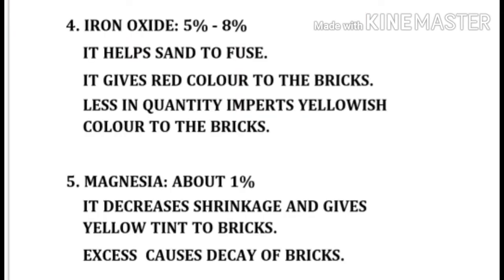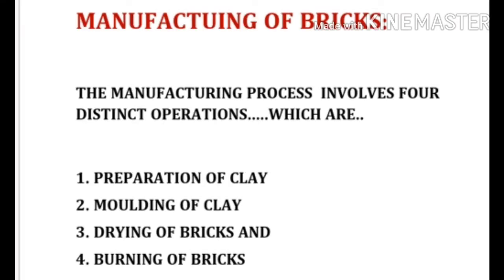Number three, lime — 4 to 5 percent. It resists shrinkage of raw brick; excess lime causes the brick to melt. Number four, iron oxide — 5 to 8 percent. It helps the sand to fuse and gives red color to the bricks; less in quantity imparts yellowish color. Number five, magnesia — about 1 percent. It decreases shrinkage and gives a yellow tint to bricks; excess causes decay of bricks.